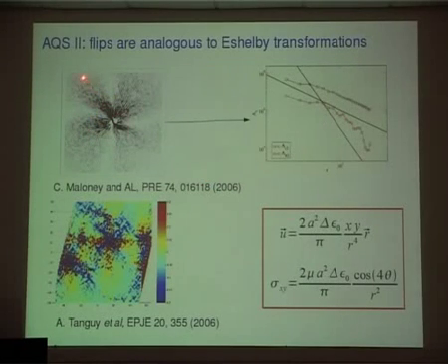For example, this is a displacement field right at the onset of a plastic event, and we analyzed it by doing Fourier transformation to find that indeed we recover the 1 over r, which is predicted by Eshelby. And this is another work where people looked at one isolated event.